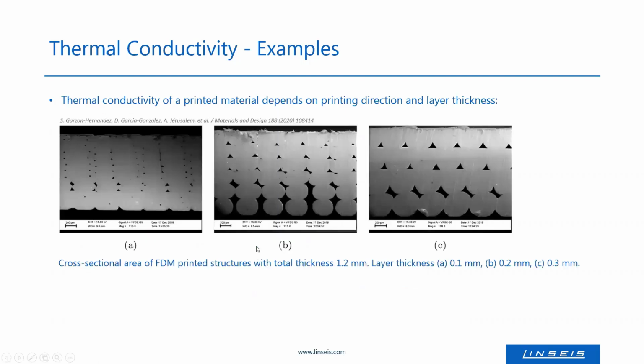Additionally, the layer thickness is also of interest. Here you see some cross-sectional scans of FDM printed structures with each a total thickness of 1.2 millimeter. The layer thickness ranges here from 0.1 to 0.3 millimeter. So you see here that really the layer thickness is of interest, since by that one can have more or fewer voids, so air in between the different layers, which can also influence thermal conductivity strongly. So here, a thermal conductivity measurement can also help to optimize the parameters.